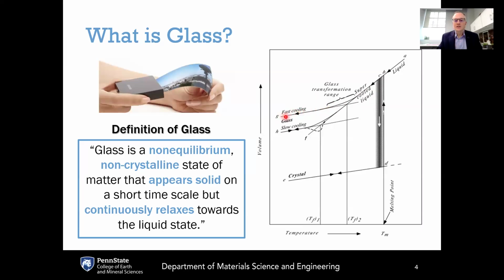And there is this continuous connection between the glass and the supercooled liquid, which is absent in the case of amorphous solids. Amorphous solids do not come from a supercooled liquid. They do not relax back towards the supercooled liquid, and their structure does not reflect that of the supercooled liquid at all. Those are the key differences between glasses and amorphous solids, that even though they're both non-crystalline materials, glasses are connected to the liquid state and amorphous solids are not.